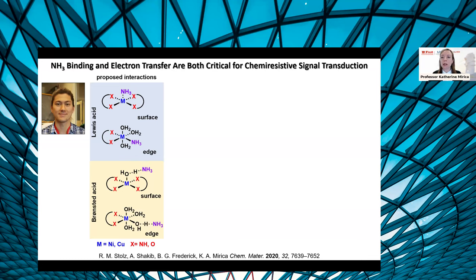But because we're in the nanowire morphology from the scanning electron micrographs that I showed earlier, likely the edge sites dominate. And because many of our devices are also randomly oriented networks of these framework crystallites, likely the junctions between crystallites and these edge sites is what's dominating the sensing response.